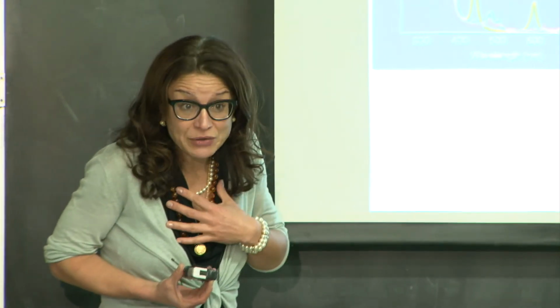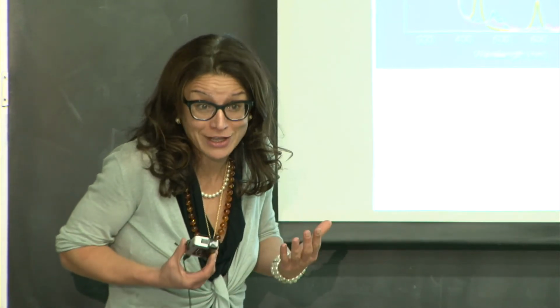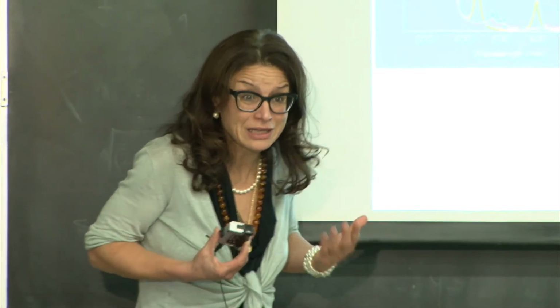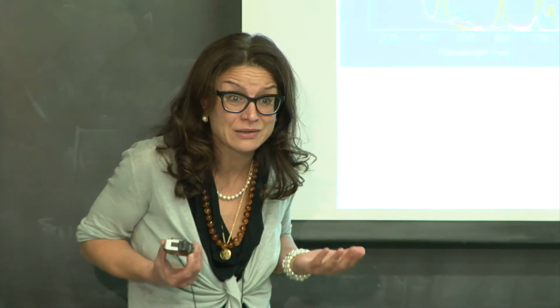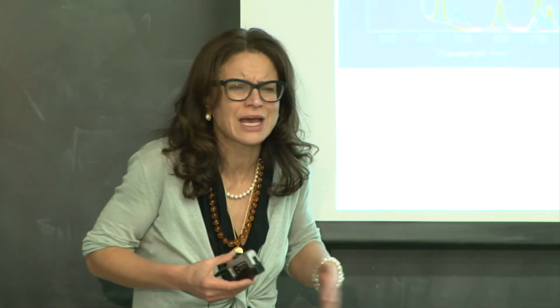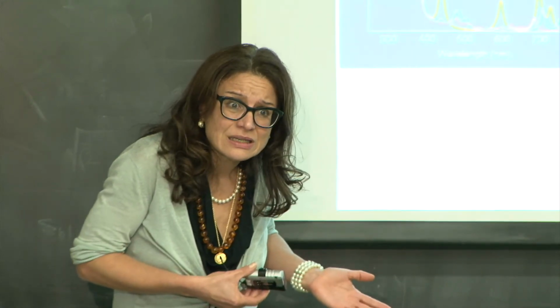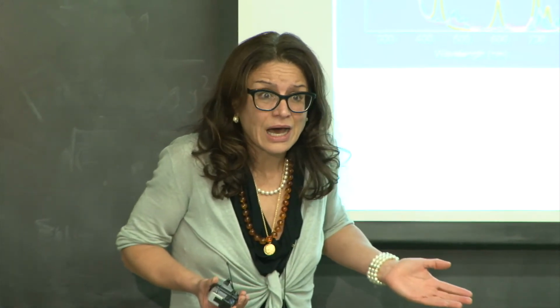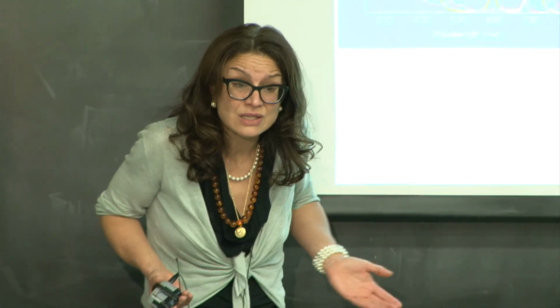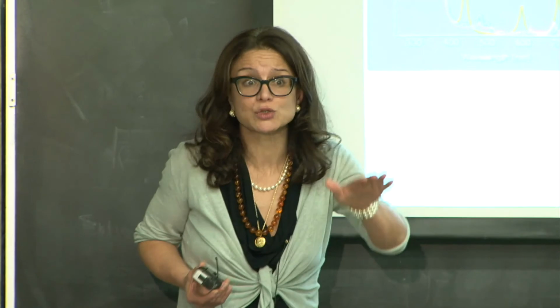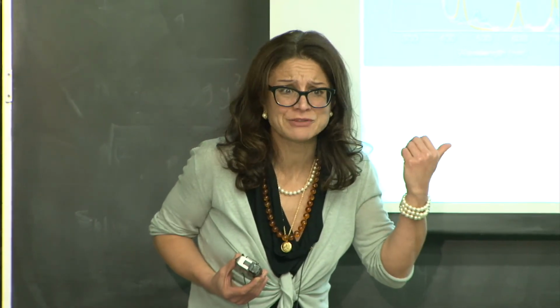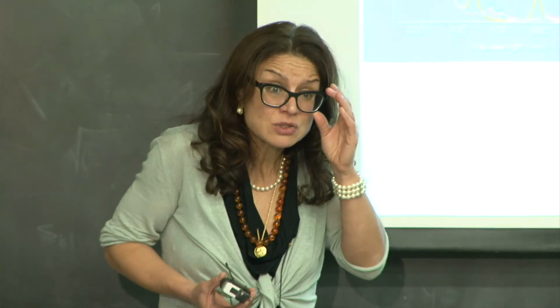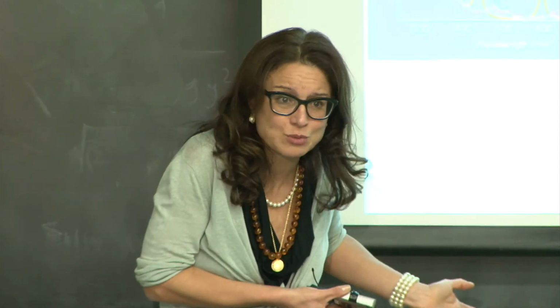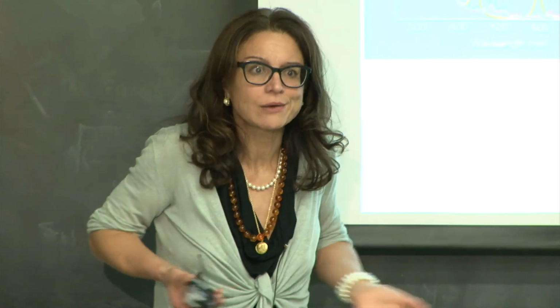My experience is that the field of organic photovoltaics has been killed essentially by the limited stability of the organic semiconductors, P-type or N-type. We see that it just survives to 1,000 cycles. Here, for the supercapacitor, we did more than 20,000. Here, I think we did 5,000, 6,000, but it seems to work. Now, it's just in the lab, an exploratory study, just an article. But these few thousand cycles are pretty decent.